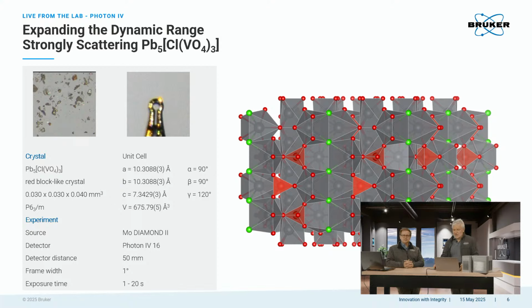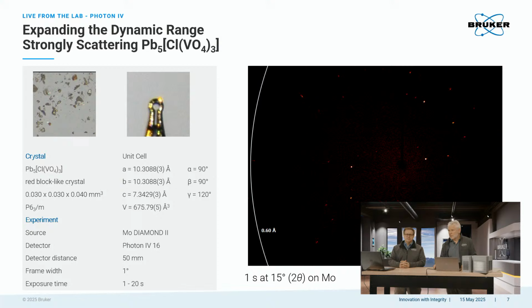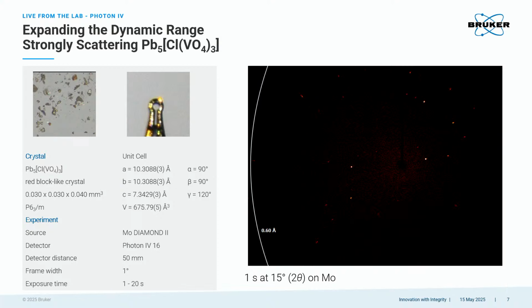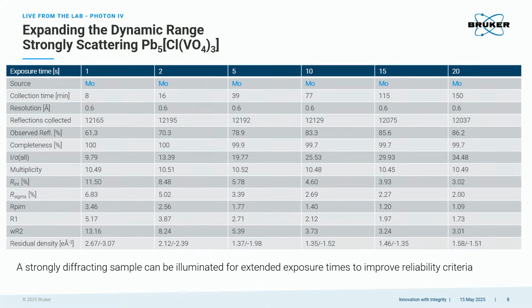Here are just some structures I want to show that they did mostly as development projects. We have this vanadate crystal that we use quite a bit. It's nasty because it has high absorption. Yeah, lead in there. It is a very strong diffractor at the same time. So here's just a very small crystal, and here's an image. Really, no background. You see strong, small reflections to high resolution. And then a data dump here.